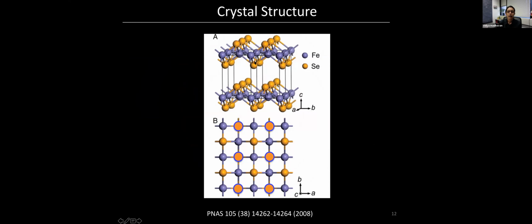You're all very familiar. One thing I do want to point out is that the top selenium atoms and the bottom selenium atoms are shifted from one another. And in STM, of course, you only see the top selenium atoms, which I have marked in orange here. And one thing to notice here is that this is the position of the bottom selenium atom. And if you think of this as just a tentative unit cell, then this thing is shifted by half a unit cell, right? So this crystal structure has this propensity to have domains where, in some region, this might be the top selenium atom, but then there might be other regions nearby where this thing simply flips. So what you'll see is a domain wall with a half unit cell shift, and that's going to be important later on.